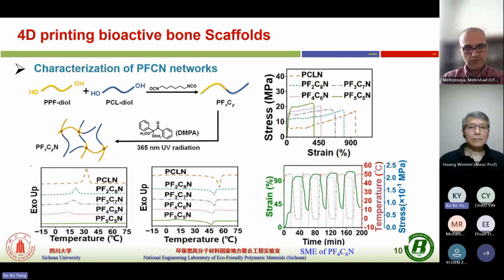The printed object can form a network, and this resulting network shows tunable mechanical strength in the range near bone mechanical performance, allowing it to be a candidate to produce bone scaffolds. The shape memory behavior of the PCL segment can also be tuned, and after optimizing its composition, we get a network with good shape memory effects.